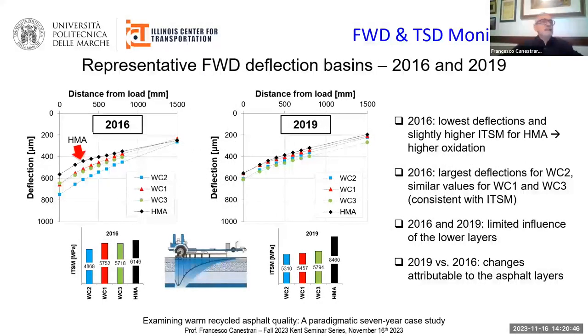The representative deflection basins obtained for all sections in 2016 and 2019 are shown in this slide. The figure on the left shows that in 2016, the HMA test field exhibited the lowest deflections, which are consistent with the slightly higher indirect tensile stiffness modulus that emerged during the laboratory tests for the binder layer. The lower deflections were probably caused by the higher oxidation undergone during mixing and compaction. The results obtained for warm mixtures in 2016 are also consistent with the ITSM of the binder layer cores.